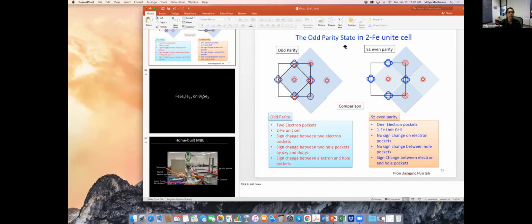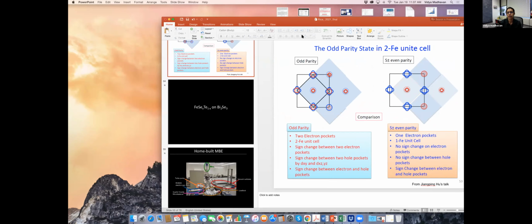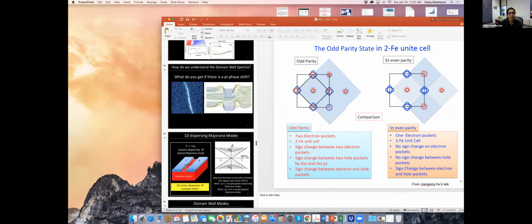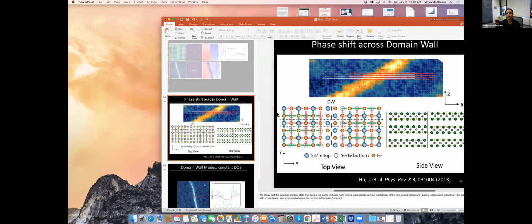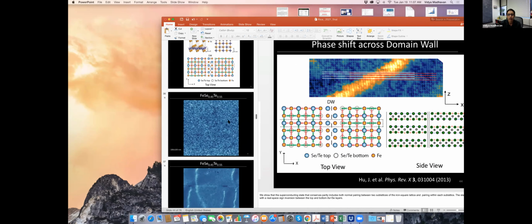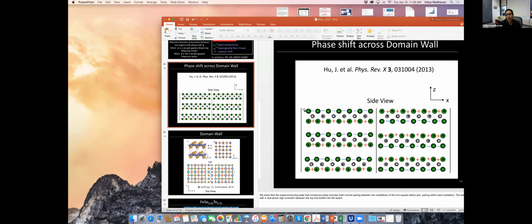Not just FeSeTe, depending upon the circumstances. He's saying many of the pnictide compounds could be in this particular state where, if you do realize this kind of effective odd parity superconductor, then not only do you have a sign change in the order parameter between the hole and the electron pockets as shown here on the right, but you also have a sign change between the two hole pockets themselves. And this is the same idea where the superconducting order parameter has the top layer and the bottom layer also show, in real space, a phase shift. So those two things go hand in hand.